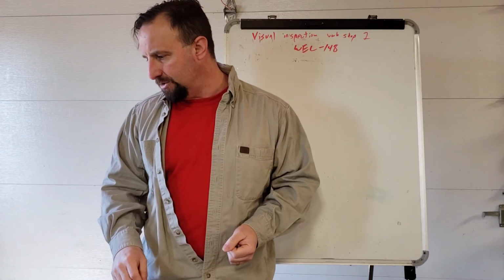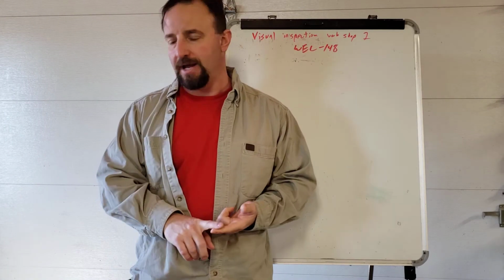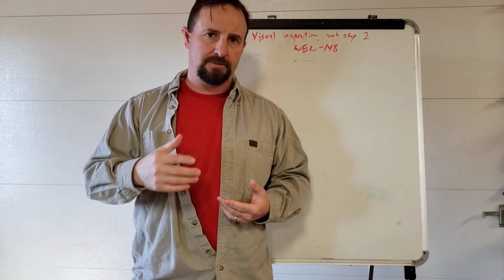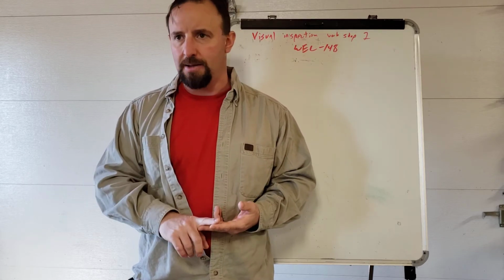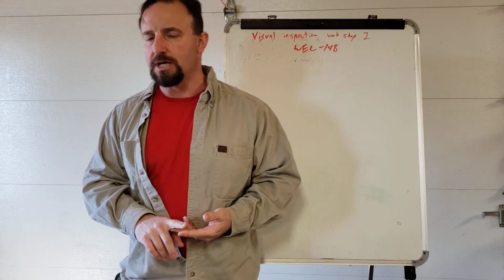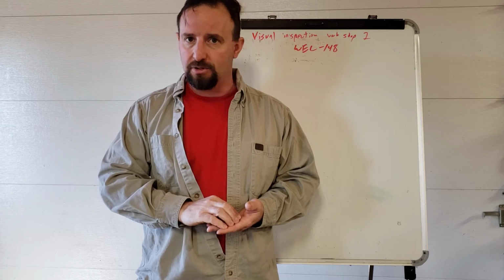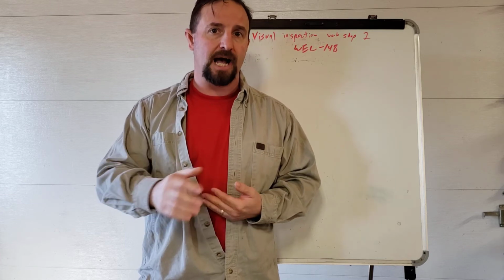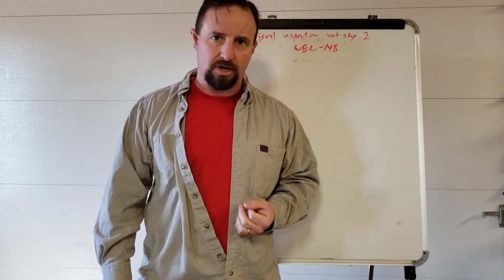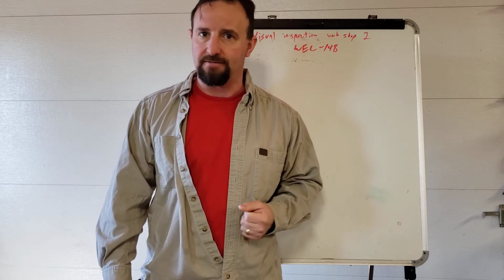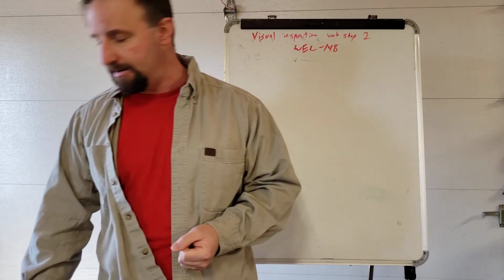Another incomplete fusion. Now on your groove face, this is where especially when you tell me that on a cap pass, on a groove weld or any sort of multi-pass weld, if I can find the edge of that weld at any given spot in time, that is absolutely incomplete fusion. The whole weld is not tied together, and that is an automatic fail. And unfortunately, I have to fail a lot of people for stuff like that.